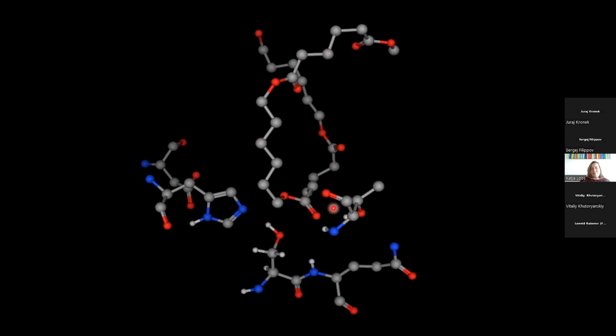And in the case of polyester synthesis, you can get very high molecular weight. And I always find that amazing because you get high molecular weight. This, what I just showed you, is inside a globular protein, which is already big. The active site is hidden inside this globular thing. And this globular thing is in such a bead. So there should be diffusion limitation. The polymer chain should actually not even fit into the active site of the enzyme, but it works.